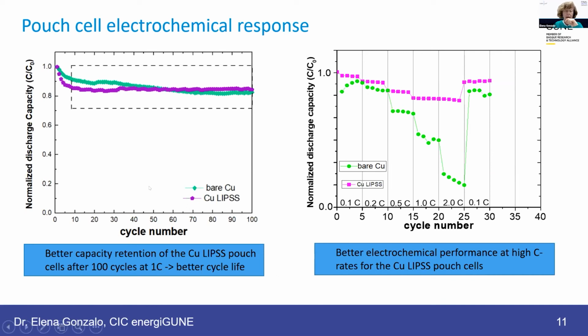On the left-hand side, we have examined the cycle life of our batteries. And we checked them at 100 cycles at a current of 1C. What does 1C mean? We were applying a current to charge the material in 1 hour and to discharge it in 1 hour. And after 100 cycles, we saw that there was better capacity retention of the copper LIPSS, the purple graph, than in the bare copper electrodes. So it means that we got better cycle life of our pouch cells with copper LIPSS current collectors.